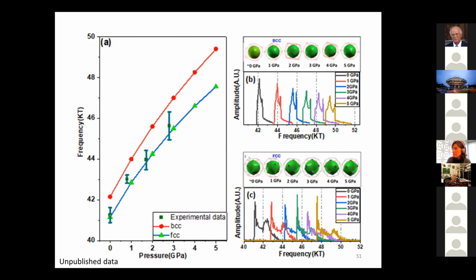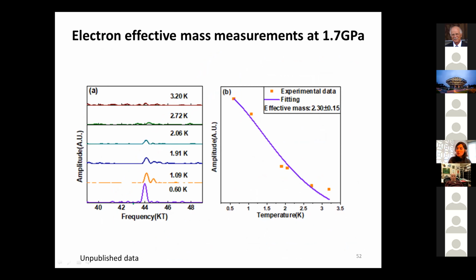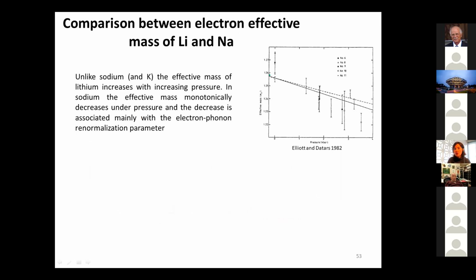Now, the next thing in every good fermiology experiment is how electrons interact with the lattice, which means measuring the electron effective mass. The way you do this is to increase the temperature and see how these quantum oscillations die off. This is what we have done at 1.7 GPa in lithium, and we see that the effective mass of the electron is 2.3. The effective mass at ambient pressure for lithium is 2.1, so there is a slight increase. When we compare this with sodium, the effective mass of the electron decreases, which means it becomes more of an ideal metal, whereas in lithium it becomes less of a free electron system. So we are really looking into this problem.